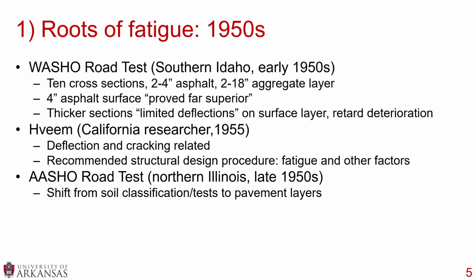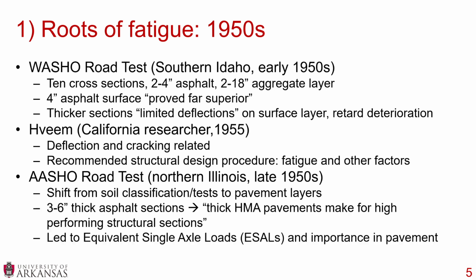Now, also around this time, we had the AASHO road test, which was in northern Illinois. This showed a shift from soil classification and soil tests to pavement layers. They looked at 3 to 6 inch thick asphalt sections, and they also found that the thicker hot mix asphalt pavements made for higher performing structural sections.